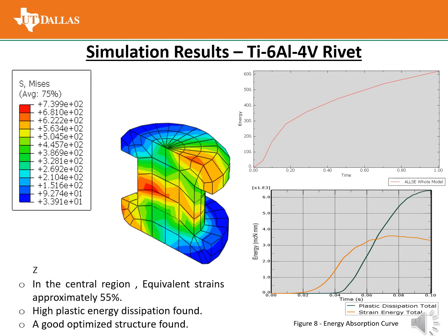The simulation results for the titanium alloy show far more promising results for energy absorption. We find plastic strains of more than 55% near the center region, but this is below the failure criteria. It is possible we get a ductile failure if there is a crack present. What really looks promising is the plastic energy absorption curve shown in the extreme right, that is figure 8, and we can see with the dark blue curve there, that shows the dissipation of energy of the rivet. This would make a good lightweight collision absorption structure.